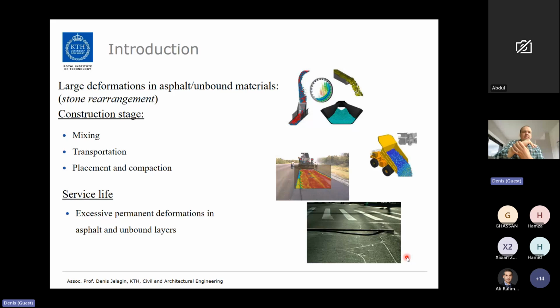And of course, the very first thing one would think about is material production and the construction stage. Mixing, transportation, laydown, distribution, compaction, all those processes are large deformation processes. And if we deal with processes where individual pieces of material change their spatial arrangement within the material, those things cannot be adequately described based on standard continuum mechanics approaches, one needs something else. We can also have those large deformations during service life in the field. We can have excessive permanent deformations both in asphalt, but especially in unbound material layers. This problem is also of big importance for railway ballast layers in the field.